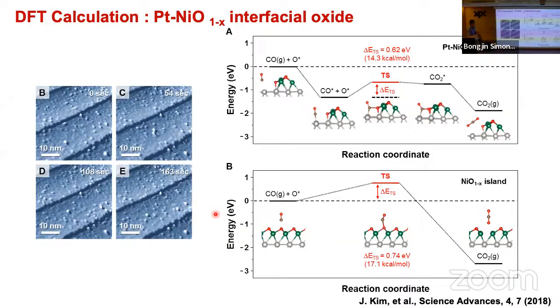So here is the idea, because I'm going to refer to this graph later on: the oxide that is being formed is actually coming through to the top surface, breaking this kind of terrace. It's not coming from the step. It's from the terrace. Somehow it's coming up, and that means the 111 surface under the oxygen is actually not stable. It'll actually be lost.